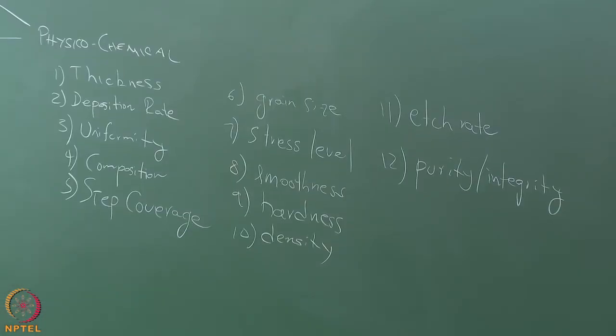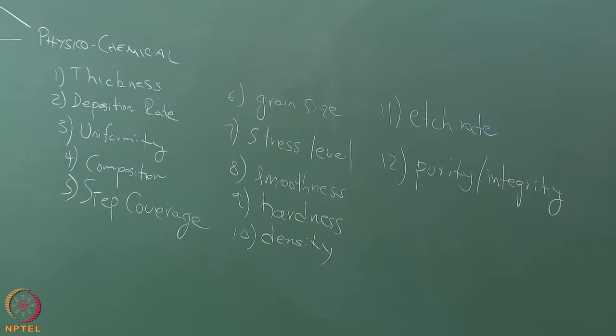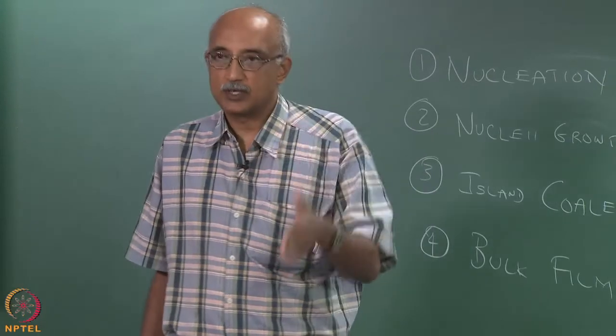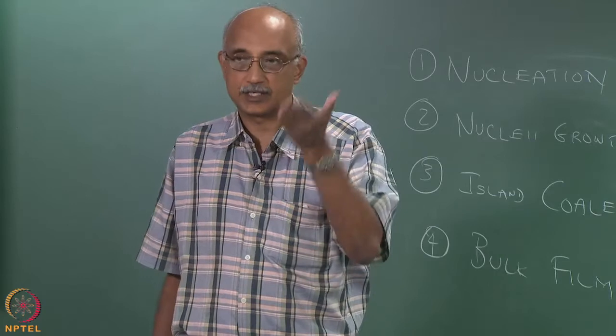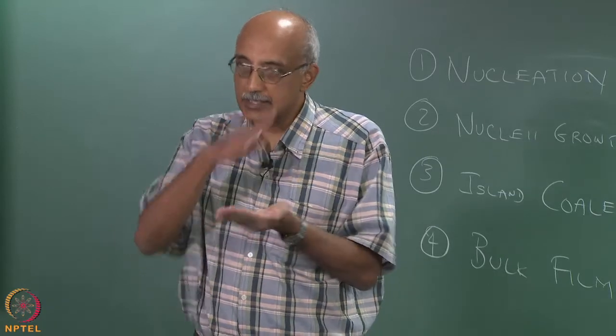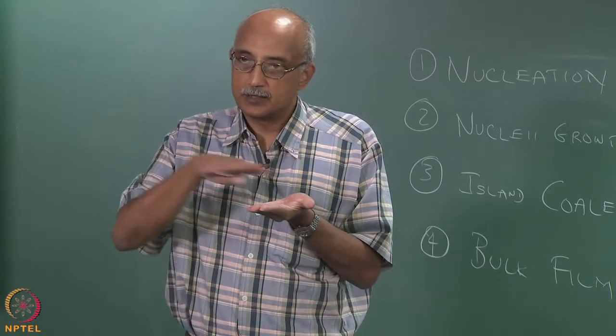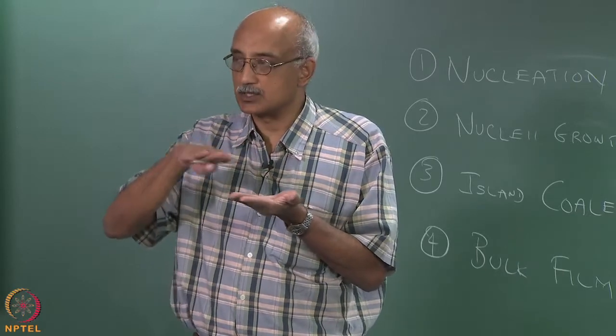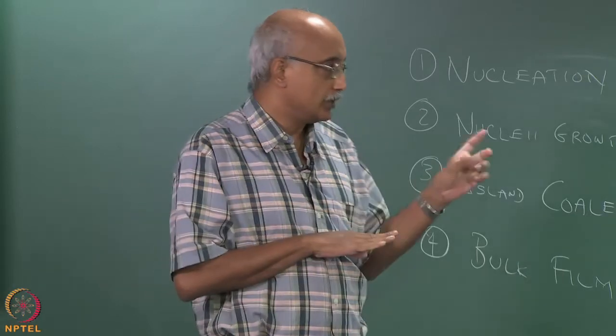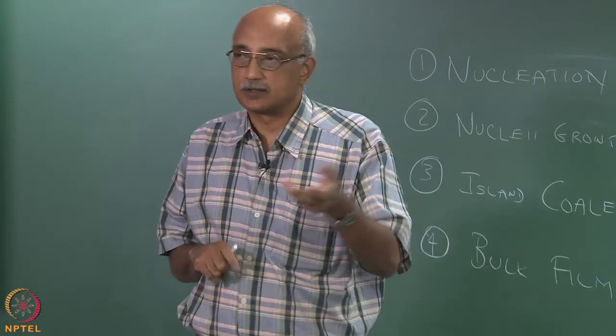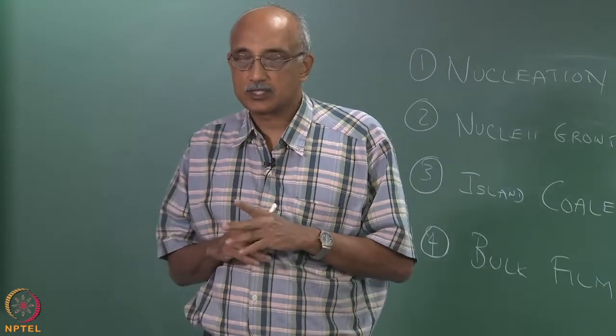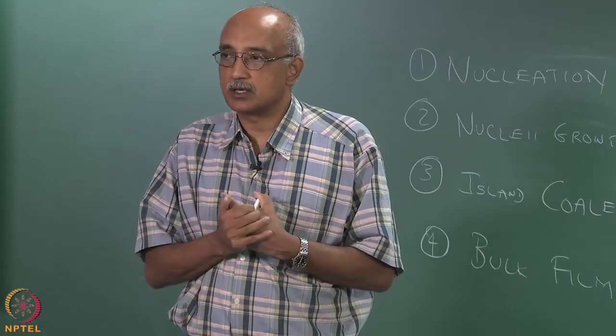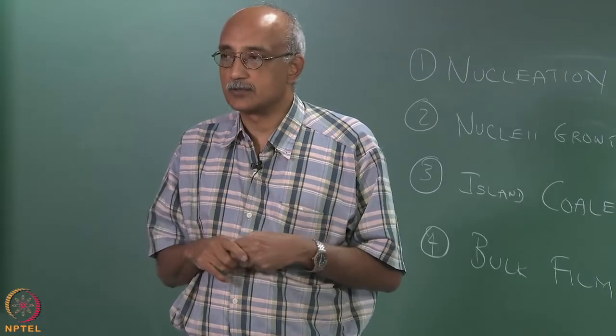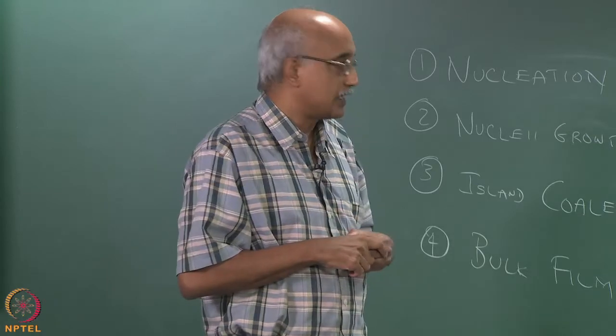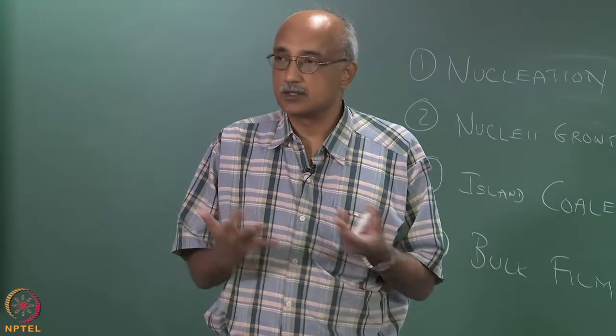Purity is essentially the level or concentration of impurities in the film. Integrity refers to how that purity changes as a function of the depth of the film. So in other words, if you slice the film and you looked at the impurity levels at each cross section, the purity typically refers to the outermost layer. Integrity is a reflection of how well the impurities are contained throughout the thickness of the film, that is in terms of compositional or chemical integrity.